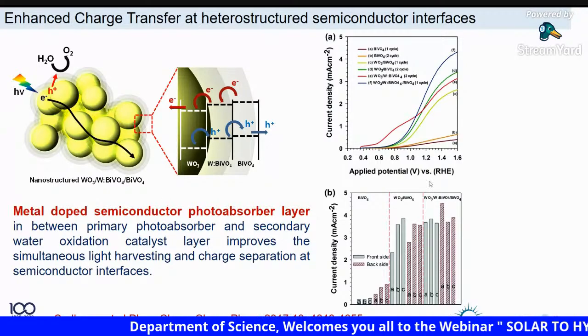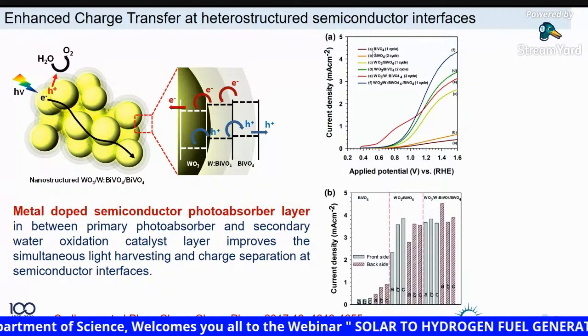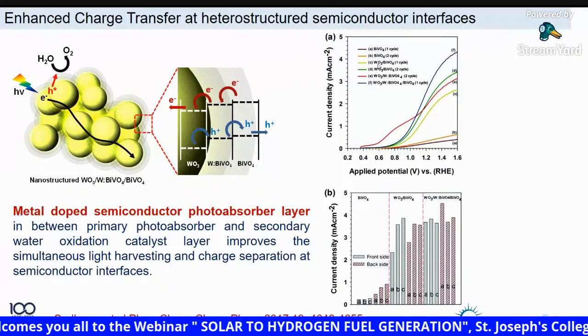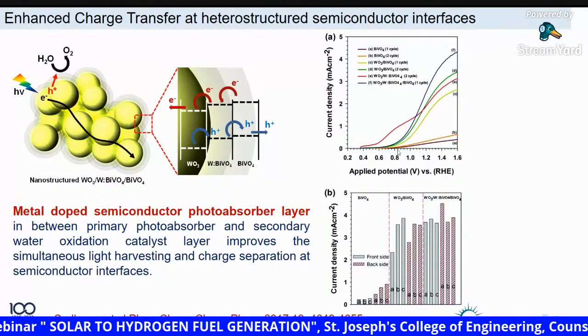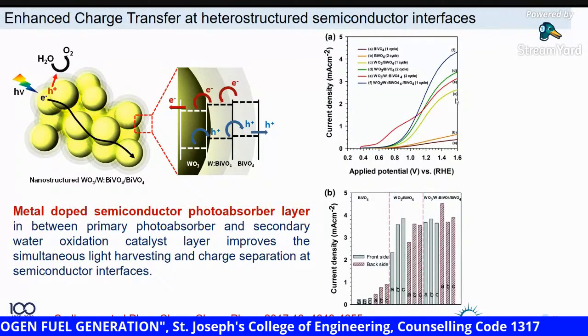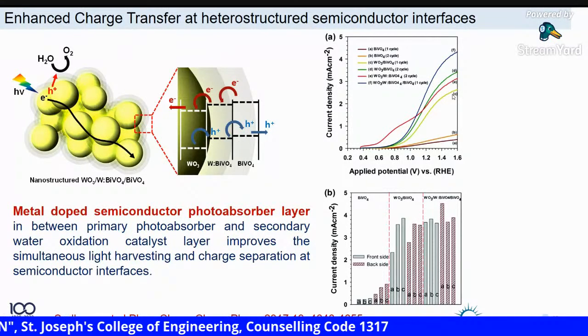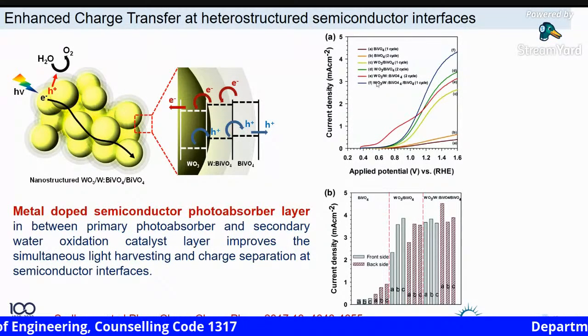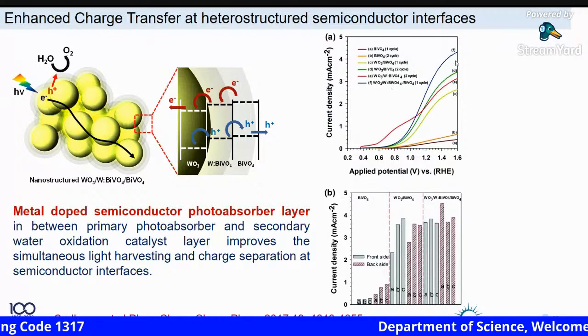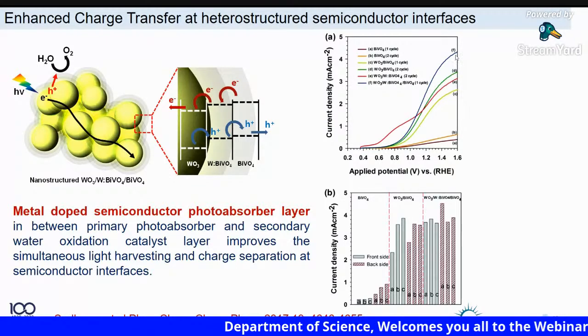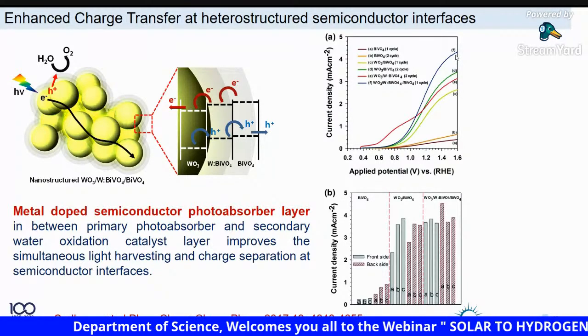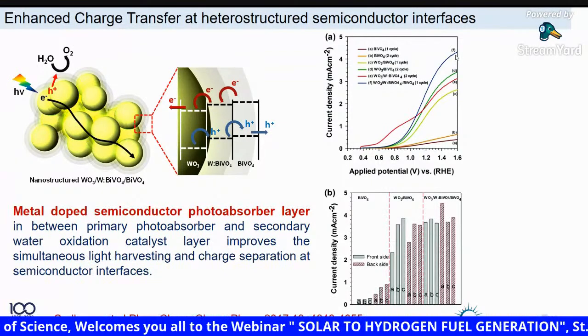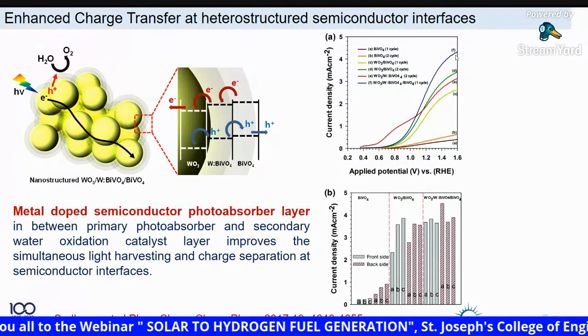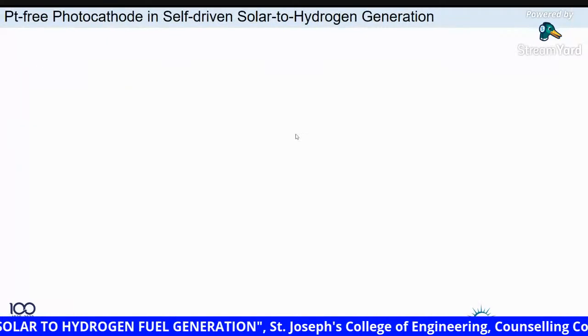So obviously, you compare only bismuth vanadate and WO3 bismuth vanadate without the interfacial layer, here the green color, indicated C. After inserting the sandwich layer, I mean the interfacial layer, the current density is drastically improved. That means something has happened or been promoted in the photoelectrocatalytic water splitting process. So this is one example.